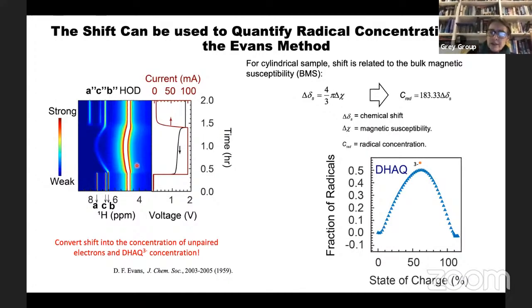I now need to explain this shift. This is actually a practical in the physical chemistry lab: you can relate the shift to the bulk magnetic susceptibility of a liquid. This is the water resonance, or technically the HOD resonance because I'm deuterating my electrolyte. If the local field changes because I have radicals in there, that gives you a bulk magnetic susceptibility shift. I can relate that to the susceptibility of the electrolyte, and use that to quantify the number of radicals, and so quantify how much of this DHAQ3- semiquinone I'm forming.